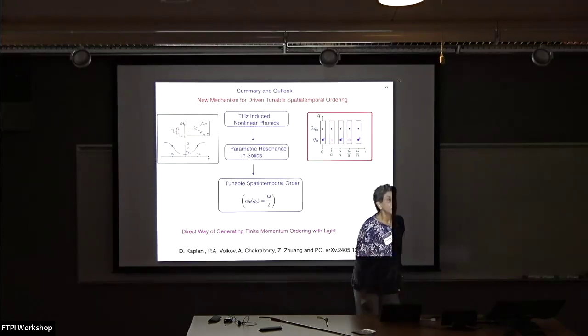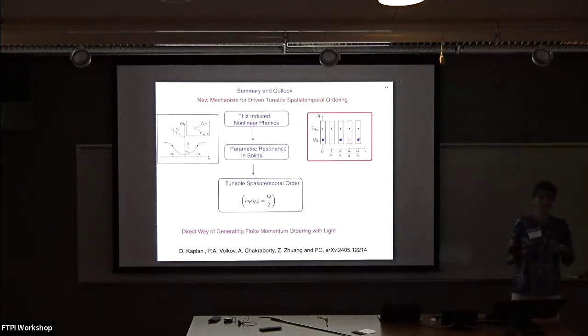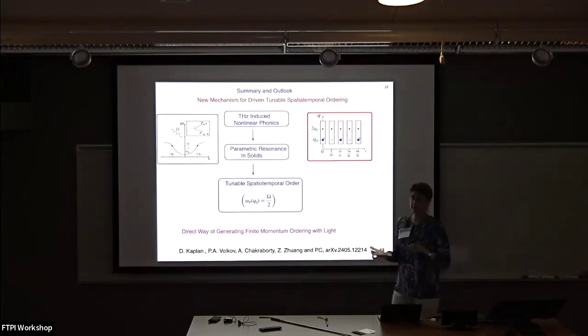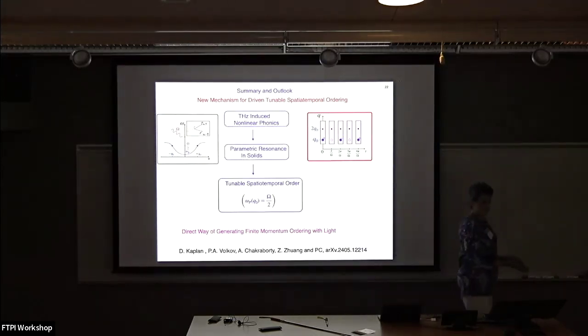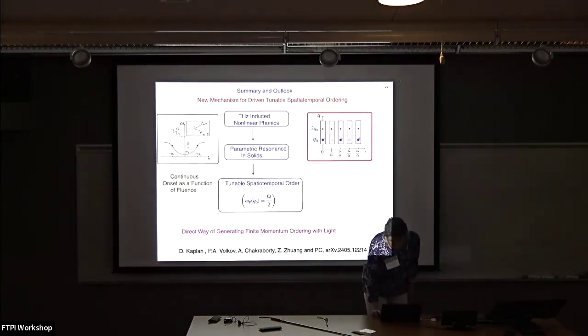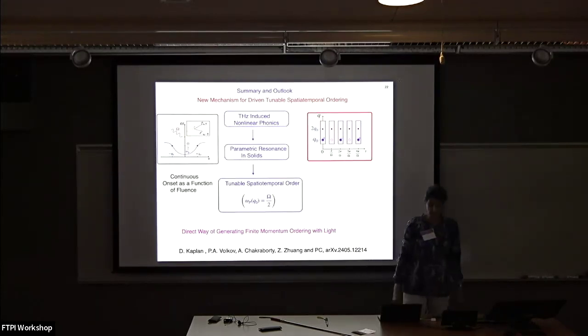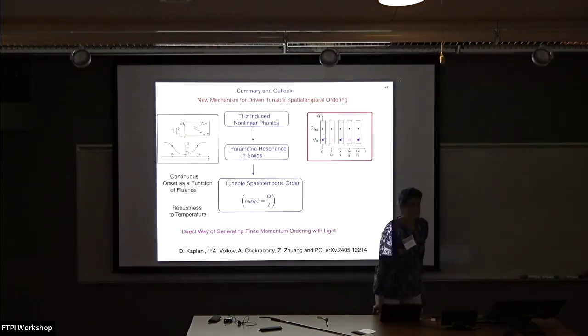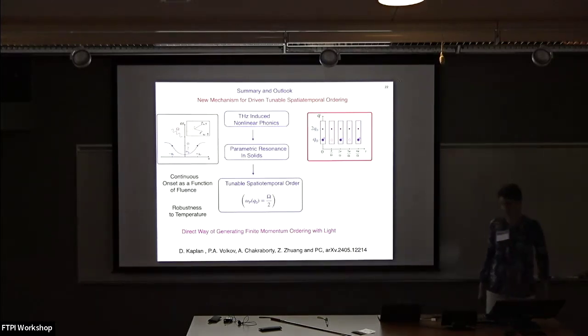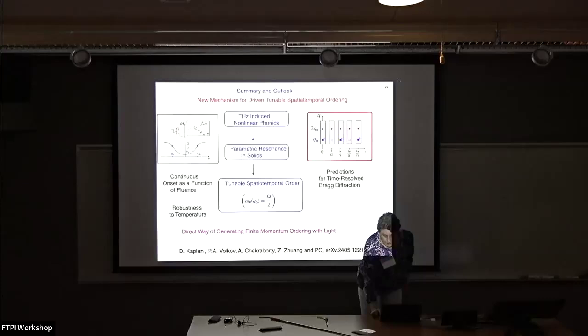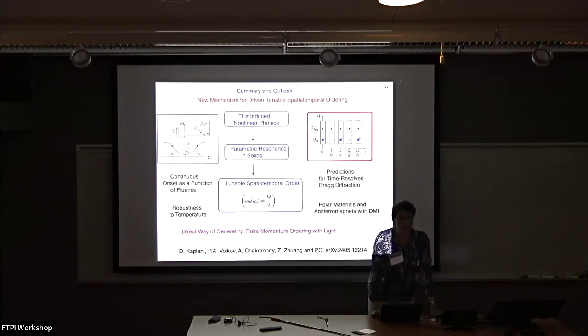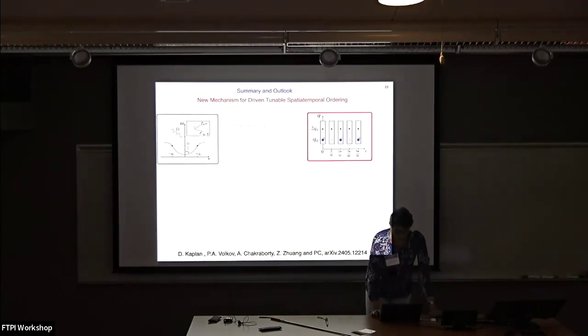Of course, electric fields are uniform. It's very difficult to transfer a finite momentum to a solid. So this is a direct way of generating finite momentum ordering with light. It's a continuous onset as a function of fluence. It's amazingly robust to temperature. That's something we want to look at more and understand. There are predictions for time resolved Bragg diffraction, and we believe that this is applicable to polar materials and also to ferromagnets with Dzyaloshinskii-Moriya interactions.